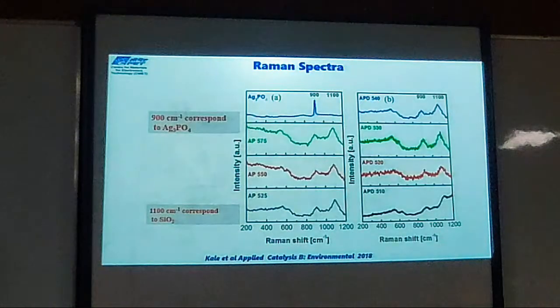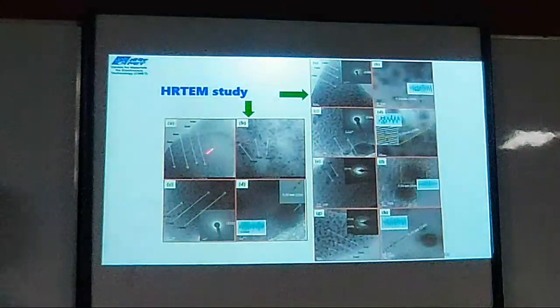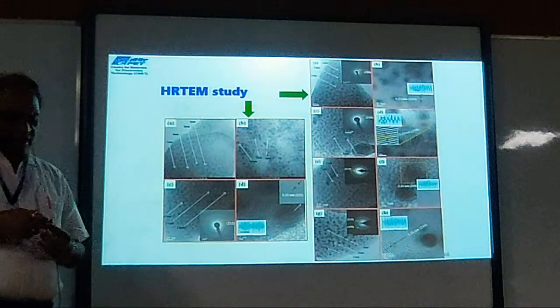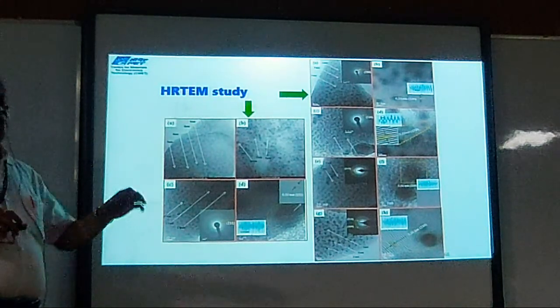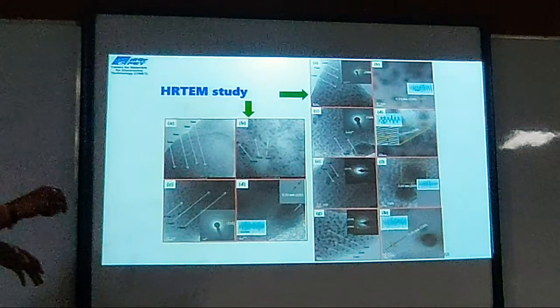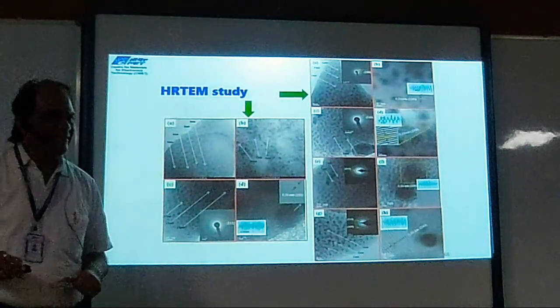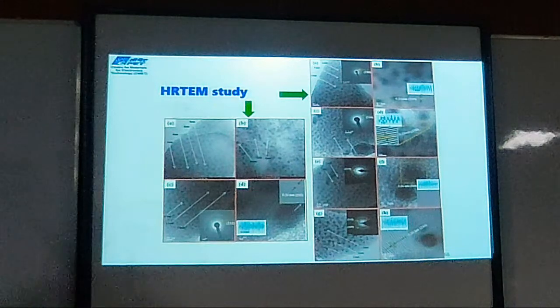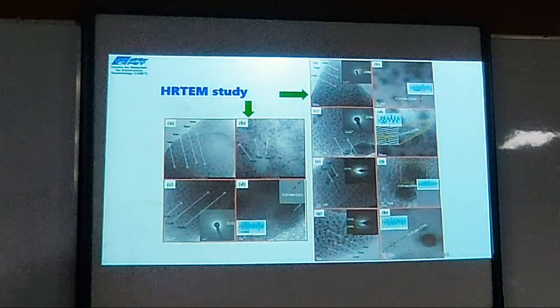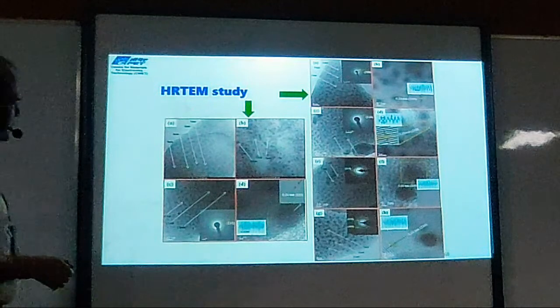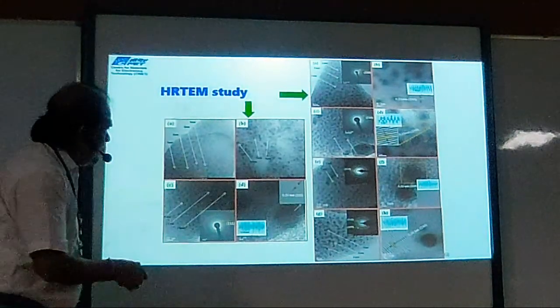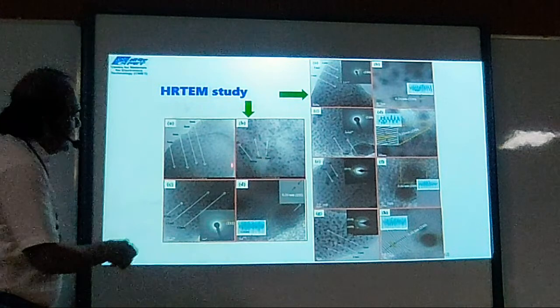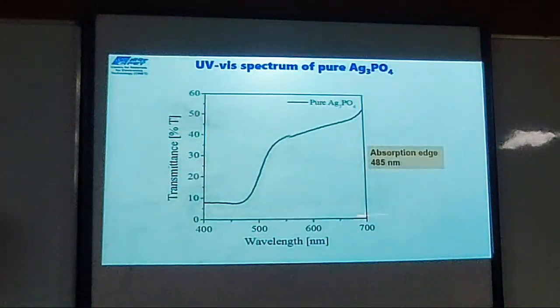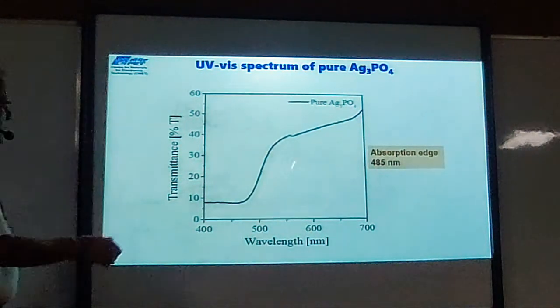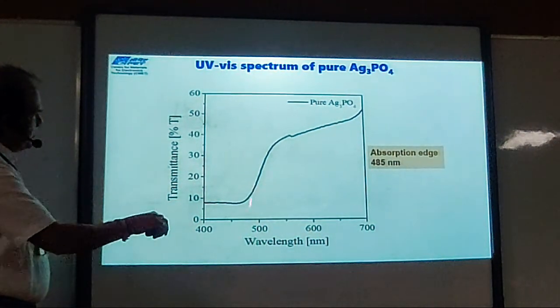And this we supported with Raman. Then you can see a very important thing. This Ag3PO4 has a dodecahedron structure, and in glass also we found they have a dodecahedron structure. Microscopically also we can see that the dodecahedrons are formed, maybe 5 to 7 nanometers. This is a powder of Ag3PO4. It's unstable. It can have 500 nanometer absorption here.